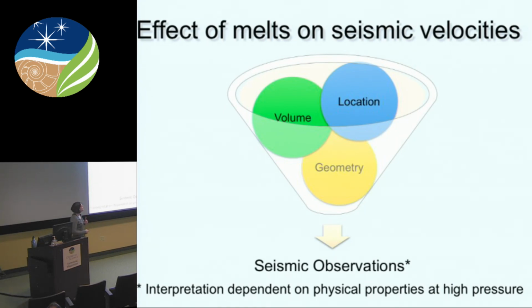To understand what is leading to observed low velocity zones, we need to know things like the pressure dependence of velocities for melts. That will give us an idea of the volume we would predict and the melt geometry we would predict at high pressure. A paper of ours, going to be published in mid-December in Science Advances, provides a new model for melt volume and melt geometry as a function of pressure in the upper mantle, and explicitly looks at coupling with the lithosphere-asthenosphere boundary.